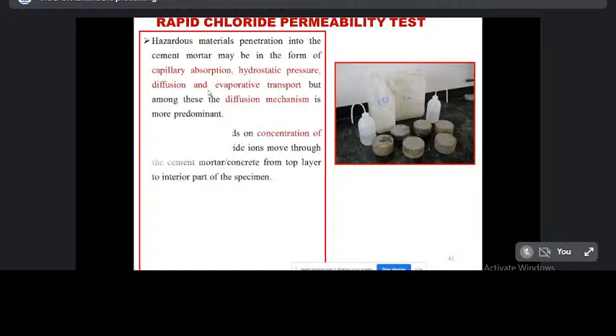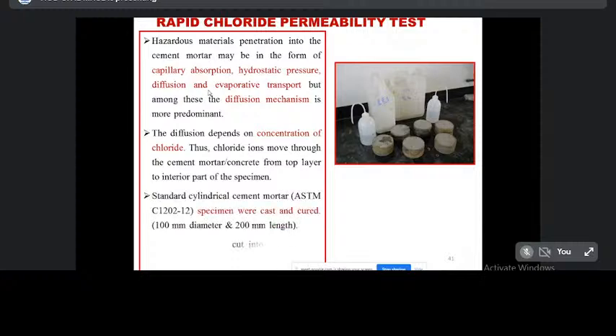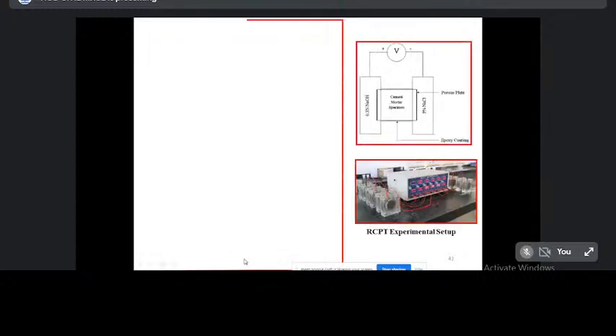Next test is the rapid chloride permeability test. For the purpose, I have made a specimen, 100 mm diameter and 200 mm length. This cylindrical specimen is cut into 3 pieces. The piece size is 100 mm diameter and 50 mm length. This is the experimental setup.